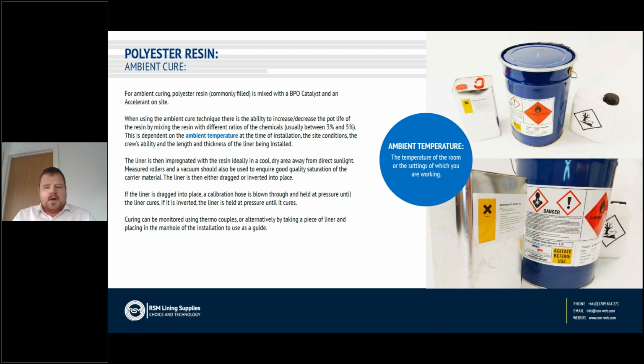In smaller applications, we use an ambient cure system with polyester resin. Commonly, we mix a filled polyester with a BPO catalyst and accelerant. This gives us the ability to increase or decrease the pot life of the resin on site, dependent on the ambient temperature, the site conditions, or indeed the crew's ability. A very experienced crew may choose to mix the catalyst and accelerant, for example, at 5%, whereas a less experienced crew who requires more working time could use a lesser percentage, but ultimately achieving the same result just over a longer time frame.